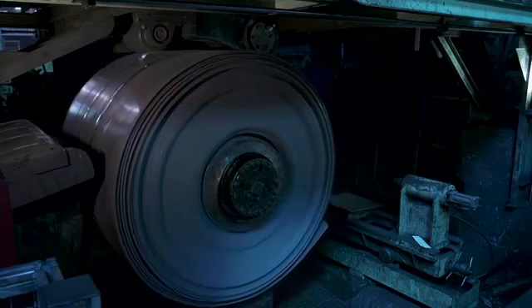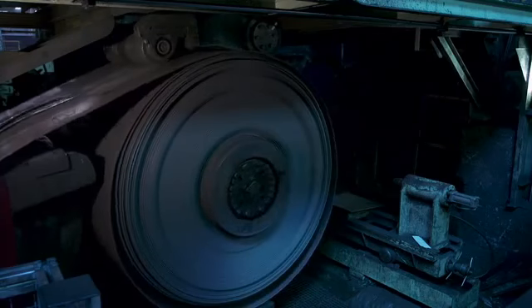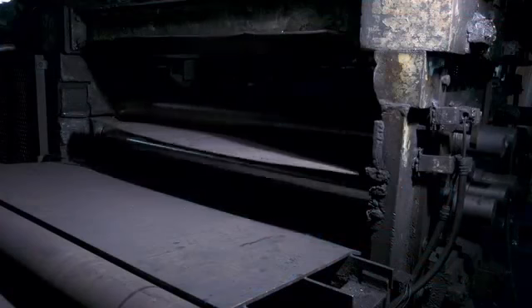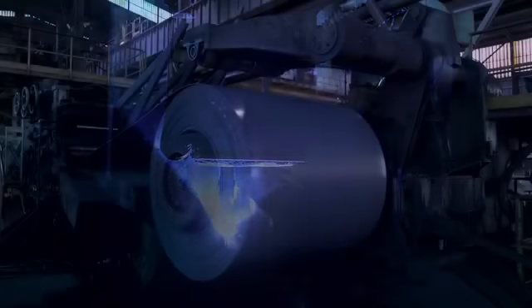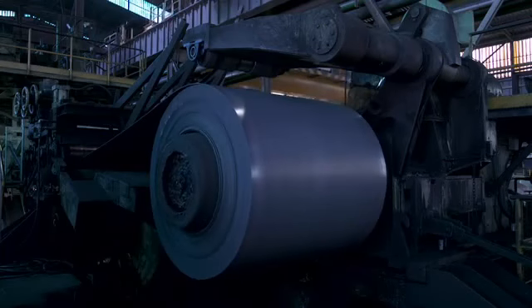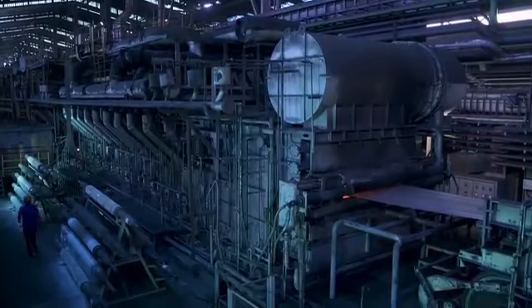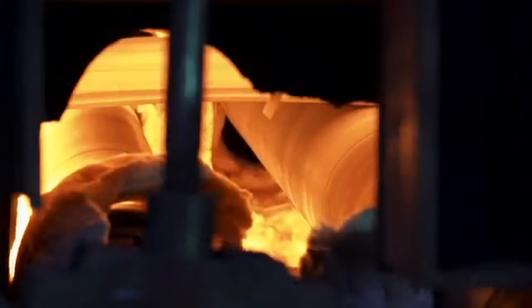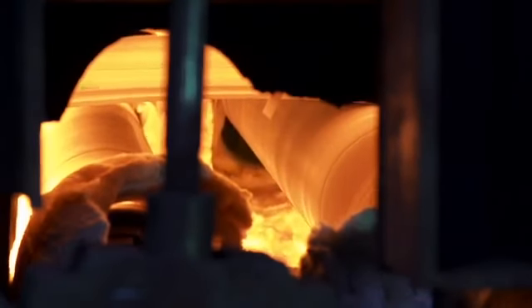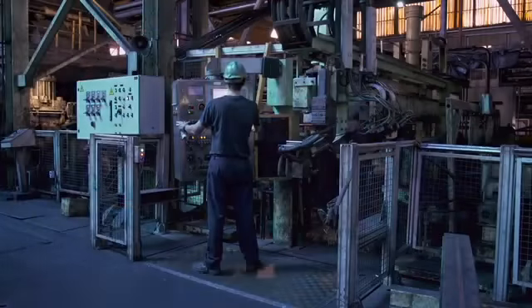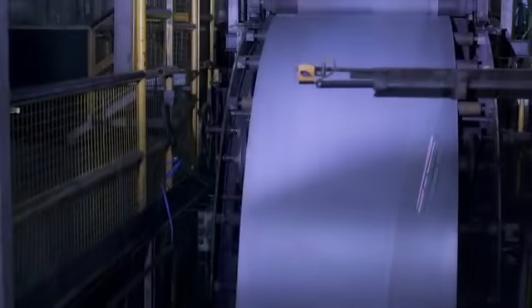After hot rolling, the crystalline structure of the stainless steel has lost its metallurgical properties. The material therefore has to undergo a thermal regeneration process to recover these properties. To optimize the process and keep it stable, the furnace works continuously so that each coil is welded to the previous one. The annealing process is a high-temperature treatment followed by a controlled cooling. In order to obtain the appearance characteristic of stainless steel, it must undergo a pickling process. The surface quality is inspected by an automated high-precision system.